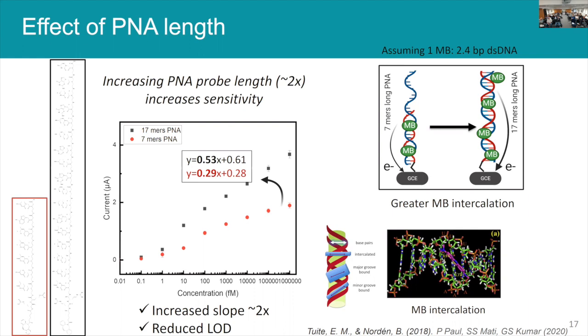What we really found interesting here, if we stop and think about it, is that there is no redox molecule in the solution where the electrode is deposited in. The only redox molecule, as I said, is methylene blue. And if we have this really long 17-mer duplex, then methylene blue is going to be intercalated throughout it. And most of my methylene blues are going to be quite far away from my electrode surface, right? So maybe like 3 nanometers to 6 nanometers away from my electrode surface.